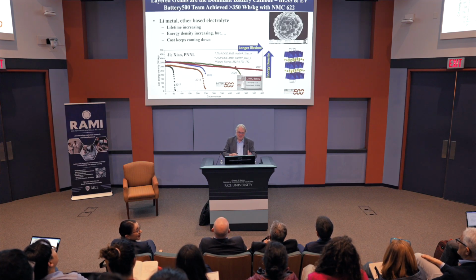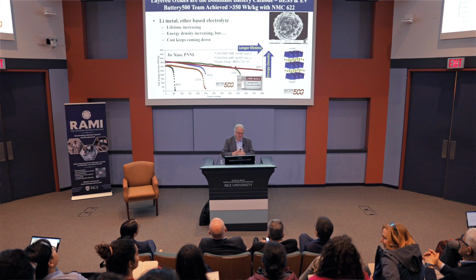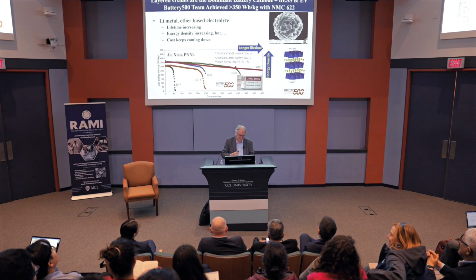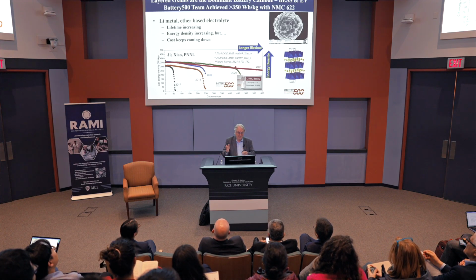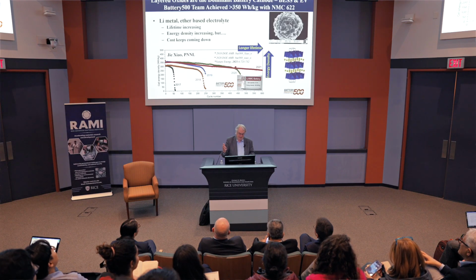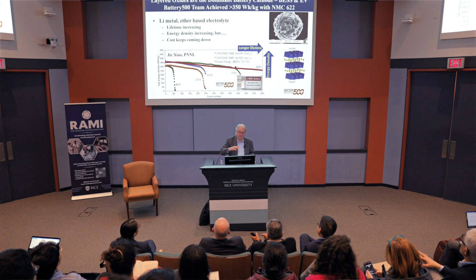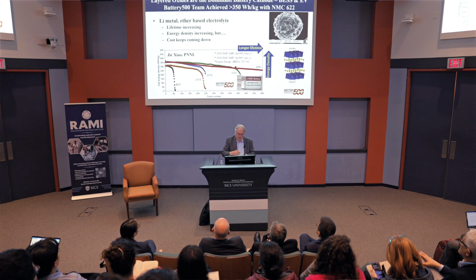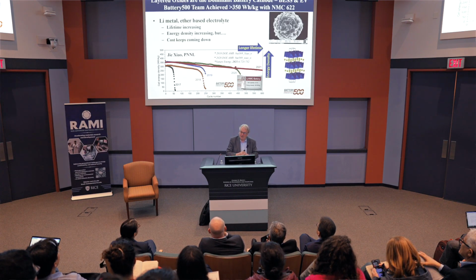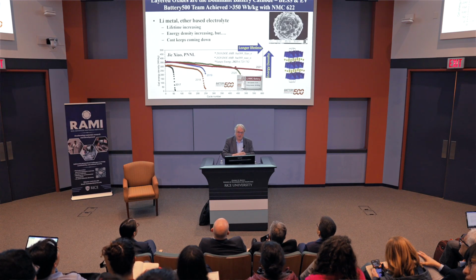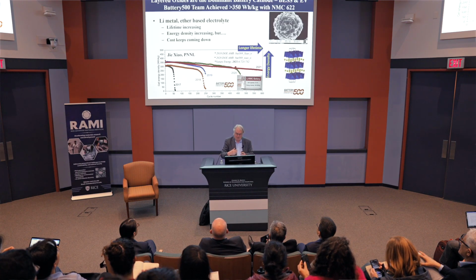But you can see here, we show you the number of cycles. Year 1 is 2017. We got maybe 50 cycles, so you could recharge it 50 times. One year later, we got over 200. The third year, we actually increased the energy density. We pushed it harder. We got the same number. And today, with this material, we've got about 800 cycles, far more than you ever need in an electric vehicle. So we've shown you can make batteries with pure lithium with these ether electrolytes that will work.